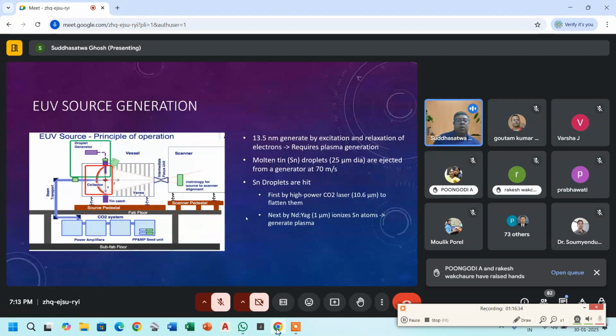So on the left side is how we do that. How do we generate this plasma? On the left, we show a brief schematic. There is a droplet generator which generates very tiny, molten tin droplets, about 25 micrometers in diameter, and they are ejected from the generator at a speed of 70 meters per second. Once they go down their path, they are bombarded first with high-powered CO2 lasers, which flatten these small droplets, and then subsequently bombarded with another type of laser, an Nd:YAG laser, which operates at 1 micron.